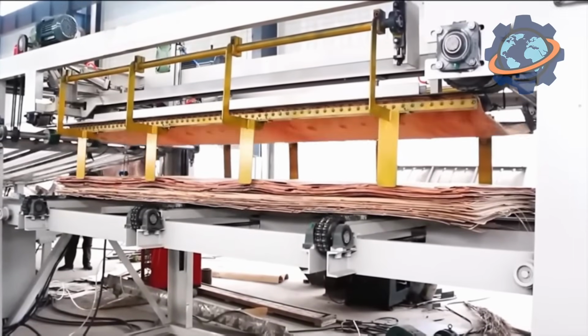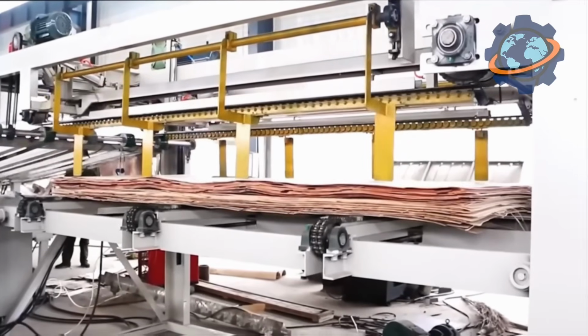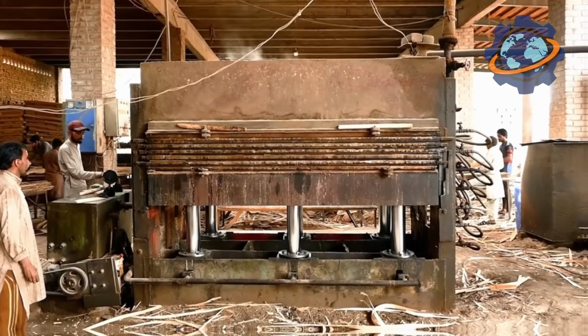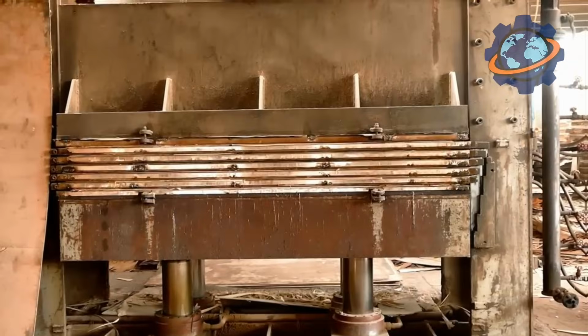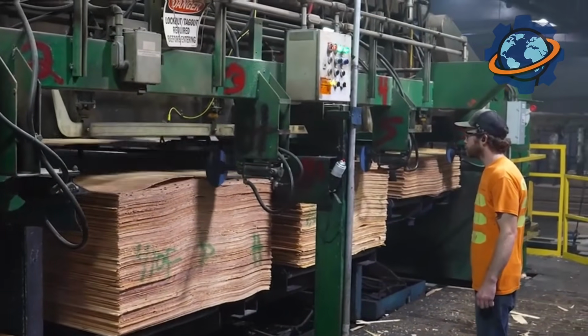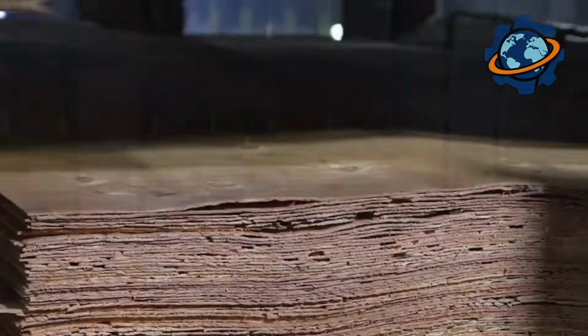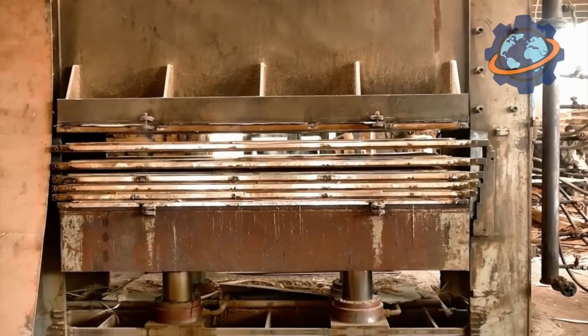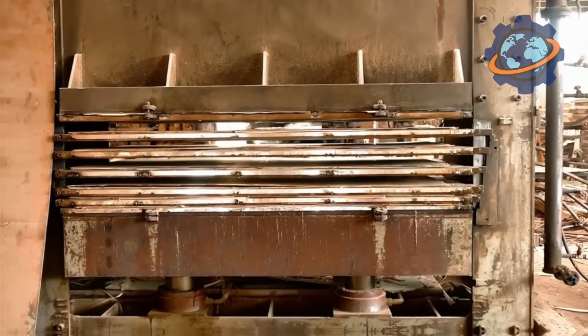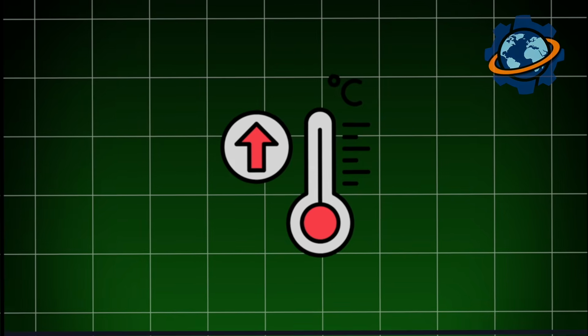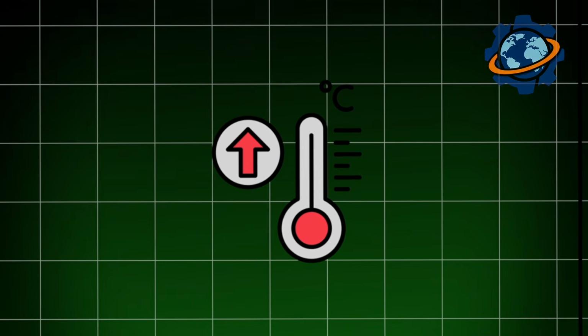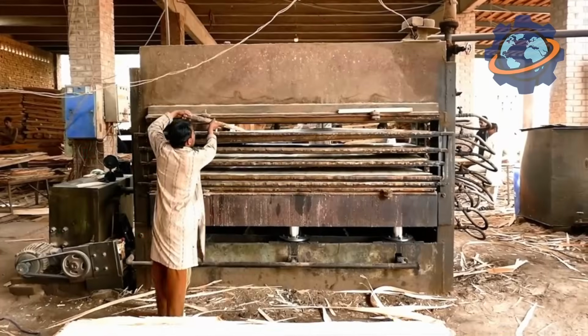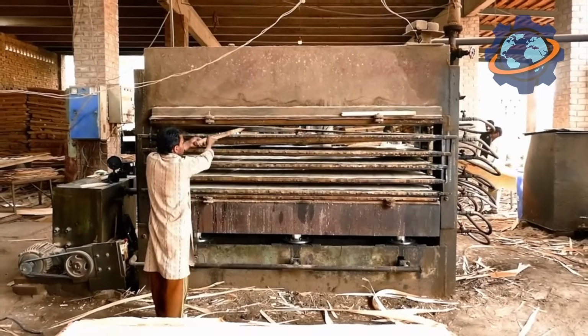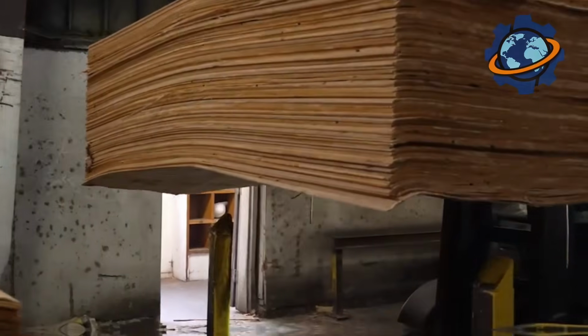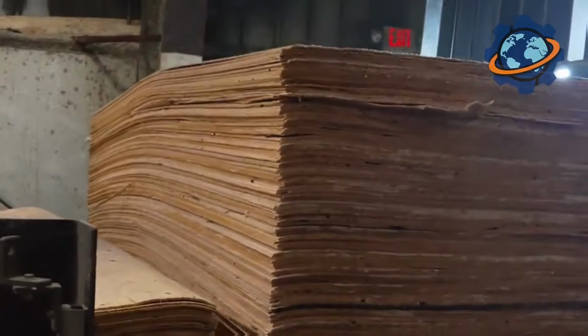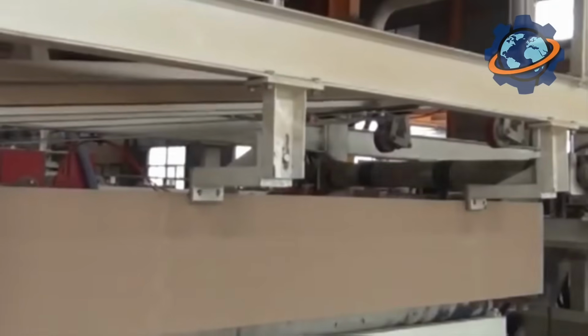When the press is loaded, the plates begin to close. With an enormous force, reaching tens of kilograms per square centimeter, the plates compress the veneer layups, turning them into dense, thin blocks. At the same time, the plates are heated to a temperature of 302 degrees Fahrenheit. Under the influence of high pressure and temperature, the glue polymerizes, penetrating into the pores of the wood and permanently bonding the layers into a single, incredibly strong monolith. The pressing process lasts for several minutes, after which a finished plywood board is born.